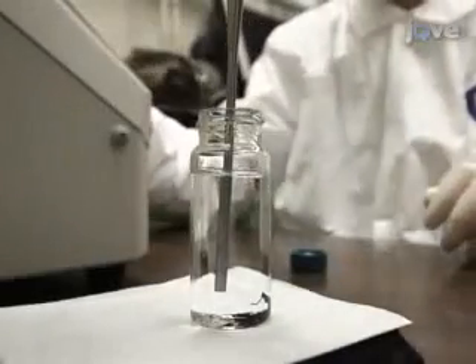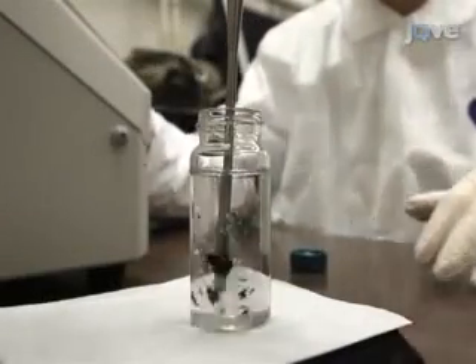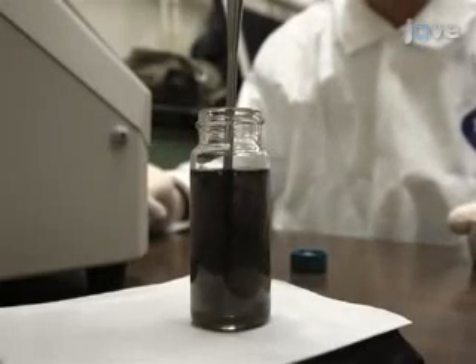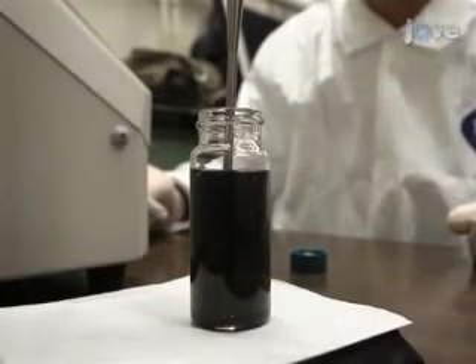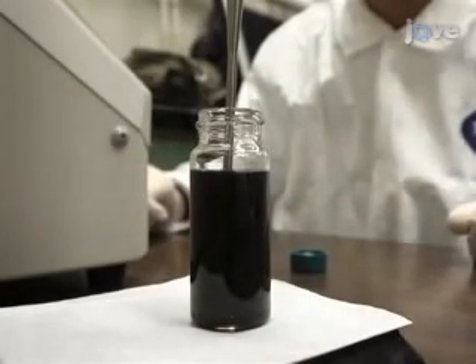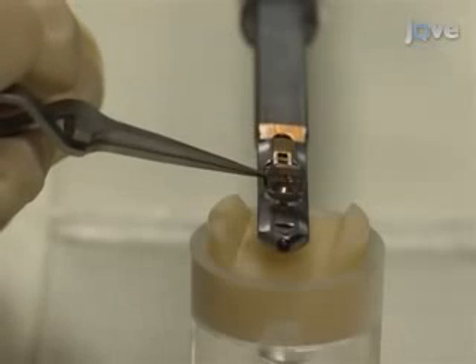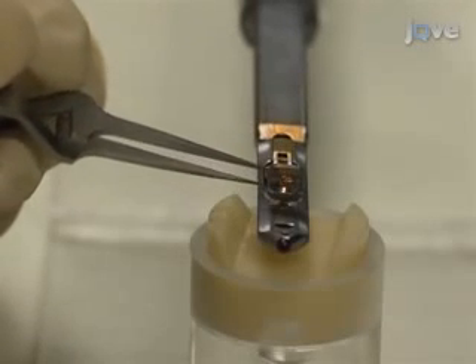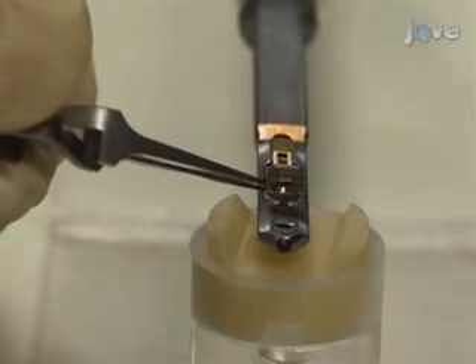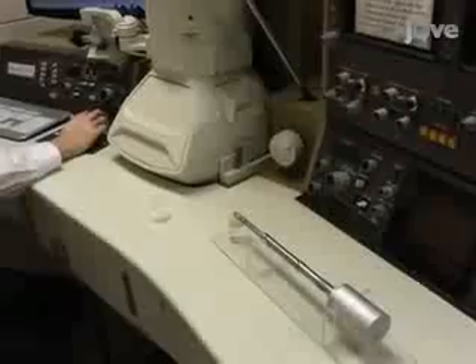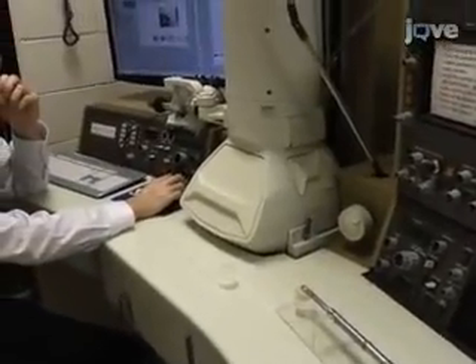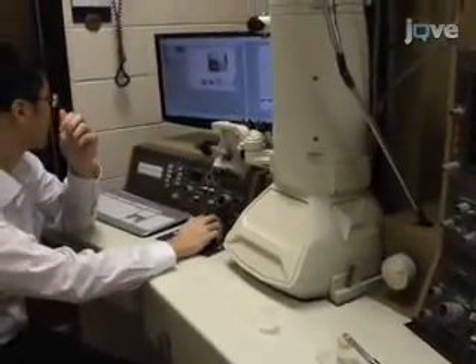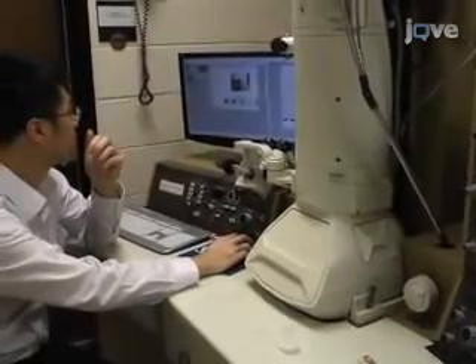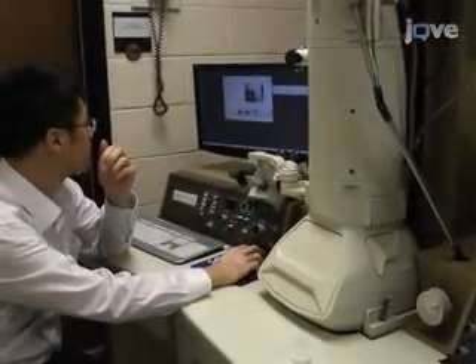To prepare samples for transmission electron microscopy, sonicate a methanol-dispersed single-walled carbon nanotube solution for 60 minutes using an ultrasonic dismembrator with 50% sonicating amplitude, then drop-cast the suspension. Observe the morphology of the film using a transmission electron microscope with a voltage of 100 kilovolts after the volatilization of methanol solution. For the position of interest in the sample, the electron diffraction pattern can be obtained with a CCD camera length of 50 centimeters.